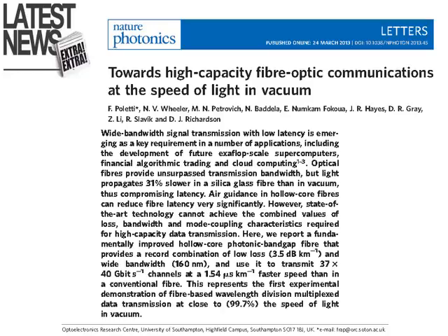Researchers of Southampton in the UK have published in Nature Photonics some enlightening results. They reported a fundamentally improved hollow core photonic bandgap fiber that provides a record combination of low loss and wide bandwidth. They used the fiber to transmit 37 40-gigabit-per-second channels at a 1.54 microsecond per kilometer faster speed than in a conventional fiber.